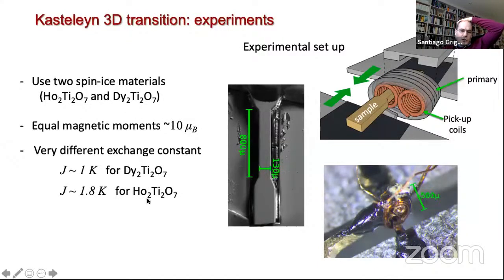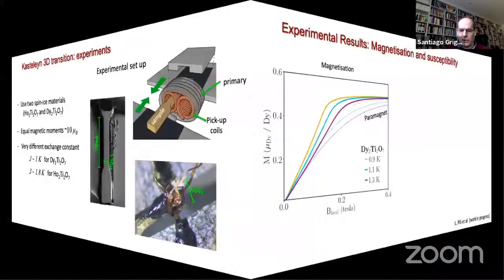What we wanted to do is to compare and contrast two different materials, holmium and dysprosium. The idea behind that was that we had these two materials that had essentially the same value for their magnetic moments. So we're expected to find this transition at the same field temperature ratio, but they had a very different exchange constant. For dysprosium titanate it is of the order of 1K, and for holmium titanate it is of the order of 1.8K, so almost twice the value for dysprosium titanate. So the idea was that if you're looking for a transition that should not be dependent on J, it's good to have a system with very different J's and see what happens, right?